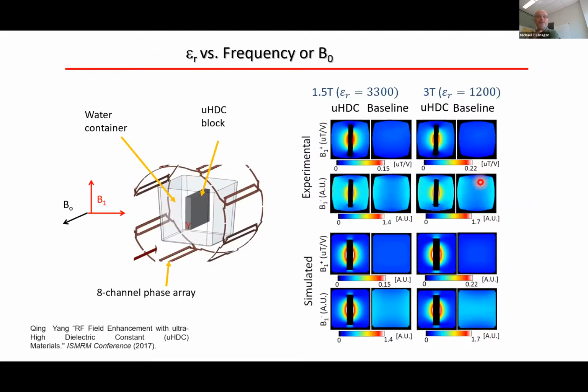The other thing that was interesting is if we actually just put a dielectric block within this MRI coil setup, and we put that block within water because we need protons actually to see the signal. Here we can compare two different magnetic field MRI units with two different permittivity blocks. So here we can see that we have the experimental and the simulated data. We have the block shown here. So that would be this scenario here. And then if we take the block out, that would be this signal strength here.